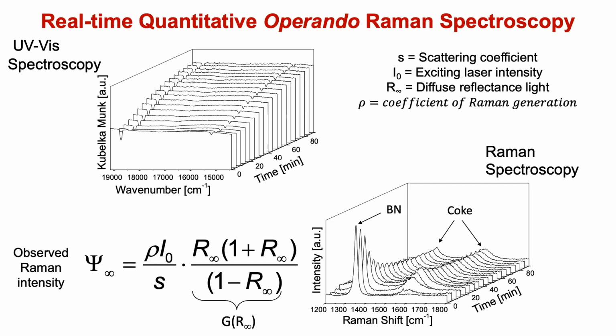What you notice, on the left top, is that the background is going up. The color is dark, the system is darkening. That you can measure, this is the reflectance. You pull that out. And these are the Raman spectra, and they are very peculiar. They go up and down. It would mean that you make more coke and then it disappears. Yeah, that's strange. That is an artifact because of the darkening, and you have to compensate for that. That can be done by taking the UV-vis and taking the reflectance and actually subtracting, not the right word, but compensating for this reflection. That can be done by this formula.